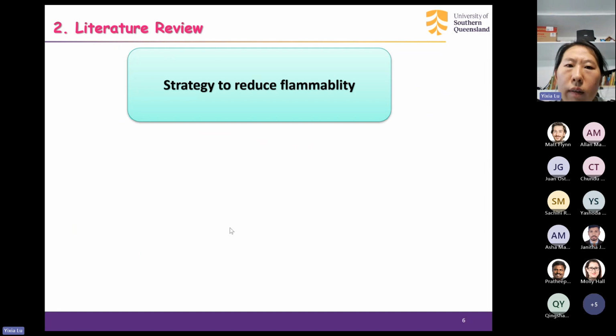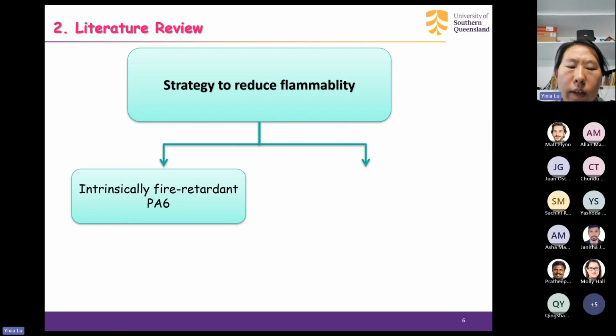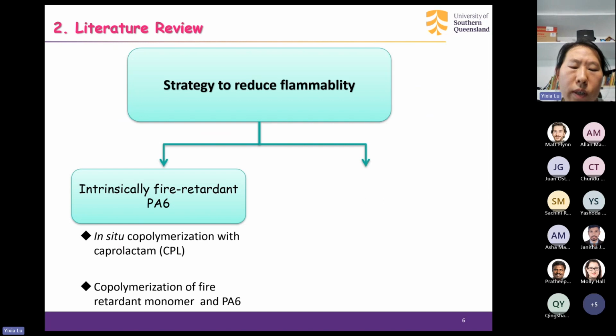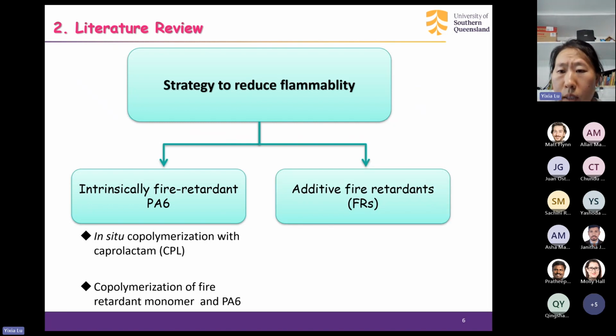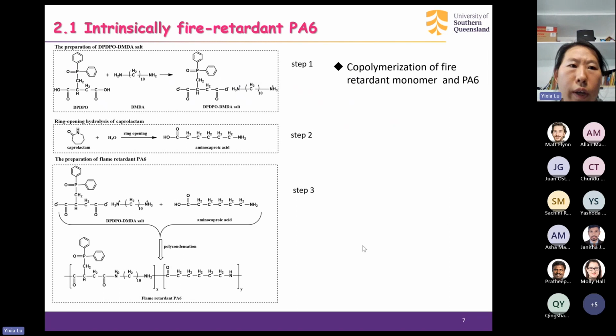So we'd like to explore some strategies to reduce flammability of polymers. For PA6, one is to synthesize intrinsically fire retardant polymers by using in situ copolymerization with caprolactam, or copolymerization of fire retardant monomer and PA6. The other one is to add some fire retardants into the polymers. I'd like to show you this example of intrinsically fire retardant PA6 by using a copolymerization reaction of this compound, and finally we got intrinsically fire retardants.